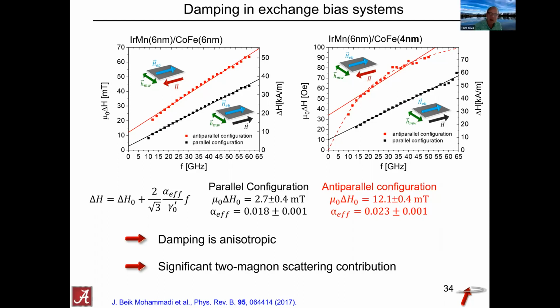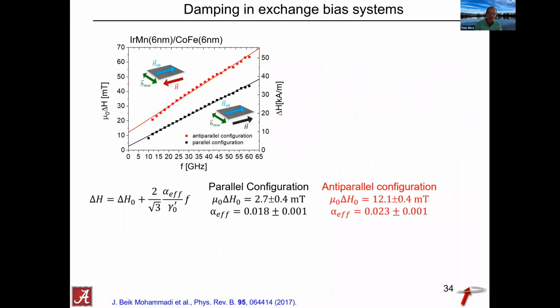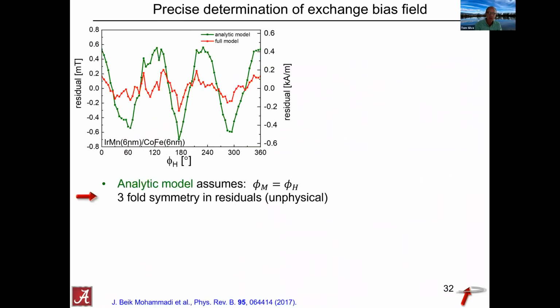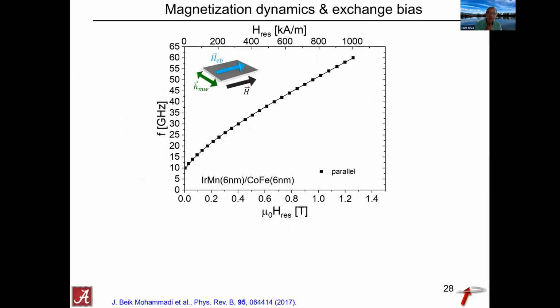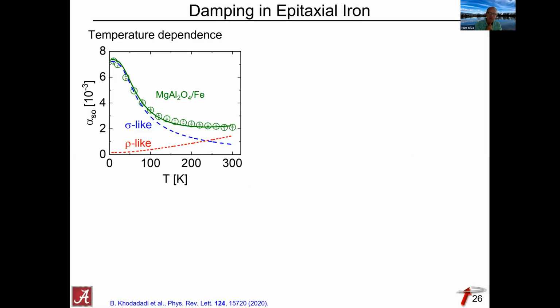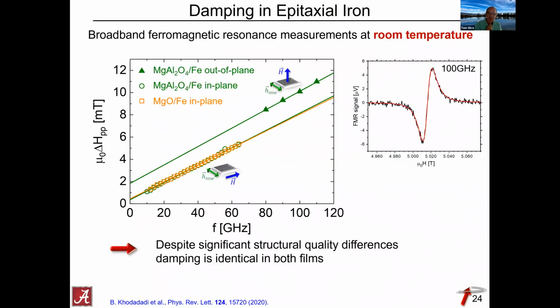Yeah, Tim. Another question came up with regard to your measurements on iron, the single crystal iron measurements. It looked like you had the same damping for in plane and out of plane, but you had a different inhomogeneous broadening. Yeah, that one. So any idea why there would be an anisotropy for the inhomogeneities in the system?